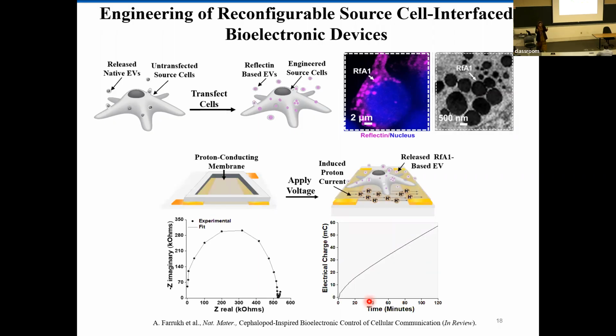Then comes the part where we prepare our devices. These are typical proton conducting devices with a semicircle and a spur. We wanted to see if we can really change the surface pH by applying a bias. When we don't have a bias, we don't see any charge on the surface, and the surface is more or less neutral, around 7.2 pH. But when we apply a bias of 500 millivolts, we see proton accumulation on the surface of the membrane. This charge accumulation results in a drop in the pH to 4.2.